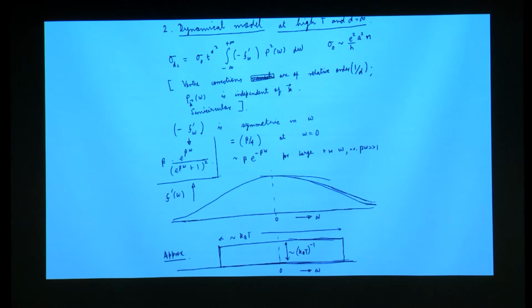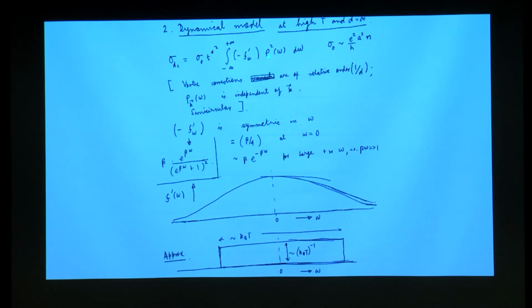temperature, to calculate some physical property, in this particular case, the DC conductivity. So the DC conductivity turns out to be some number, sigma naught, times the hopping integral T star squared, times the derivative of the Fermi function, times the square of the single particle density of states, integrated over the frequency. Now, all these are in d equal to infinity. In this infinite dimensional system, in calculating the response function via the Kubo formula, you can neglect what are called the vertex corrections. It is just a product of 2 single particle Green's functions, which are finally described by this single particle spectral density.